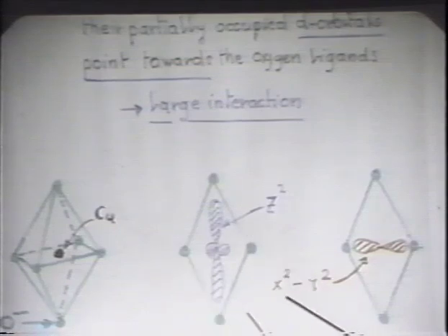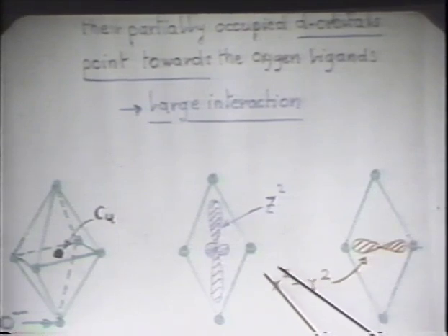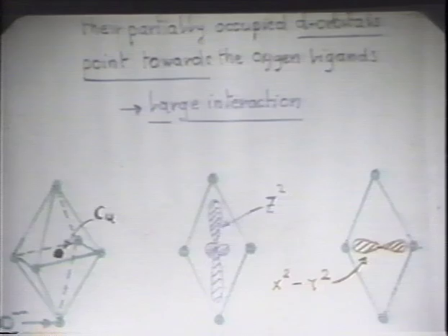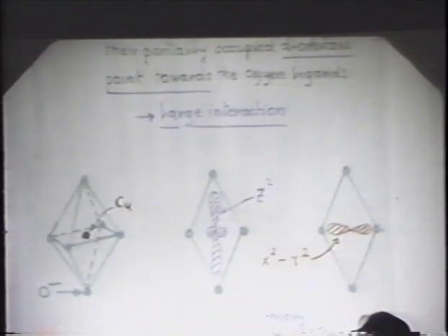And if you have a 3-valent copper, you have this z-square orbital occupied once and this x-square minus y-square orbital also occupied once. And they are degenerate in energy. If you have a 2-valent copper, then the further electron goes in this orbital here, and you get an elongated octahedron. This is an expression of the Jahn-Teller effect. Now, I would just say here, it may be important in theory to consider, especially also in the new compounds, the degeneracy between these two orbitals, and not make a theory only for a single band from x-square minus y-square orbitals. For instance, Don Lee, in a very recent theory, has done that, and he will talk about that later on in this session.